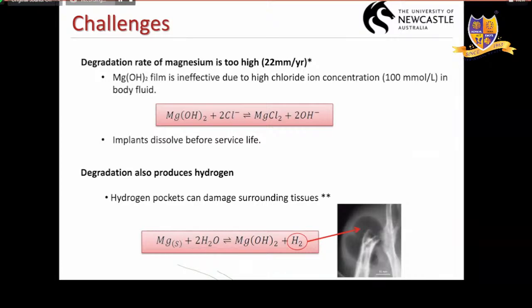There are two major challenges. The first challenge is the degradation rate. The degradation rate of magnesium is too high. It's extremely high. See, we are talking about a metal to degrade, but it has to survive for that period. I'm talking about 3 to 6 months. But this dissolution is too high, about 22 millimeters per year.